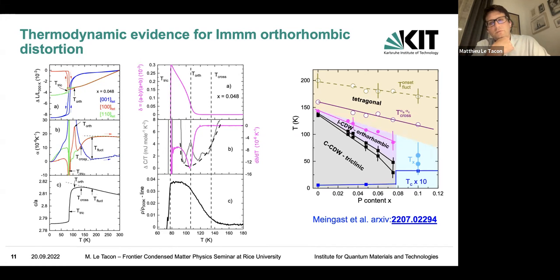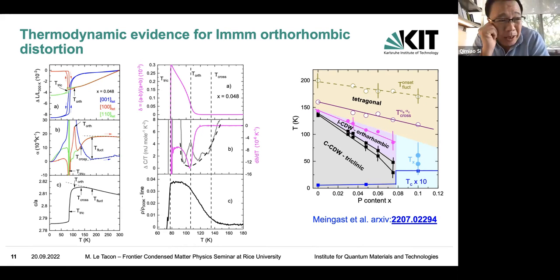which matches very nicely the onset of the broadening, except maybe for this 10% sample, which is by far the most interesting, because here we don't have any triclinic transition left. We have the higher TC, we still have the CDW. There's no orthorhombic phase anymore, and yet we still have this big splitting and this fluctuation, which starts from even higher temperature. To me, that is the most intriguing regime. And something happens here, also along the C-axis, some kind of collapse that we need to figure out.